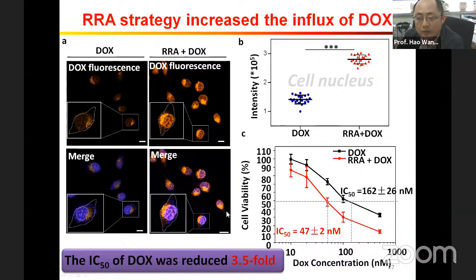And in this case, we also measure the IC50 cell viability of this combination. And we see the IC50 of the DOX was reduced 3.5-fold compared to the pure DOX.